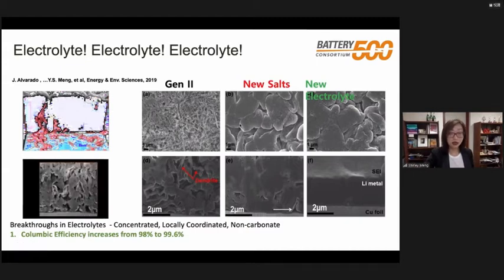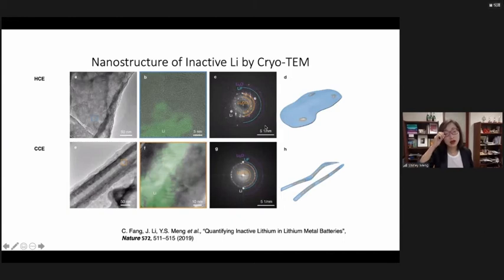So in order to understand why morphology is so important, I want to show you this TEM picture, and it's obtained under cryo conditions. You cannot obtain this kind of very high resolution image in a regular TEM, because this metallic lithium is surrounded by the insulating SEI. SEI contains lithium oxide, lithium fluoride, lithium carbonate. It's very insulating. So when you put a high energy electron beam on it without cryogenic conditions, it's not just the temperature; cryo TEM also uses a very low dose and very high detection efficiency detectors, right? So under those conditions, you can image lithium metal.